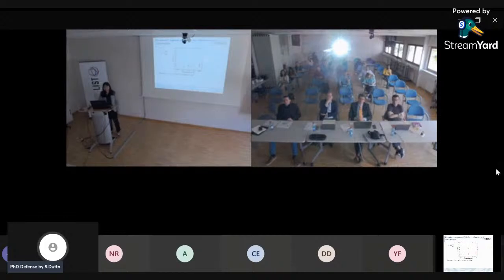Here I have plotted e33 versus silicon concentration, and initially we were surprised to see that the dispersion of e33 among the configurations is very large. We realized that the ordering of the dopant is playing a role. We did not know whether to trust this result, because how you place the dopant inside your lattice changes the response you get.